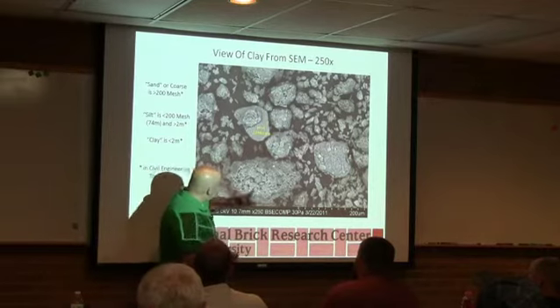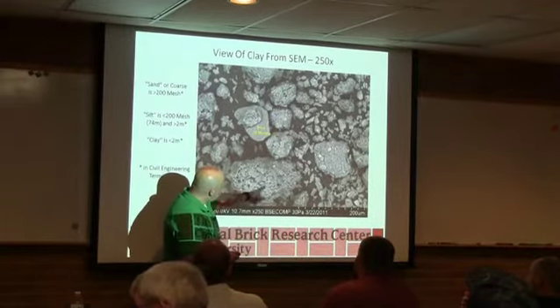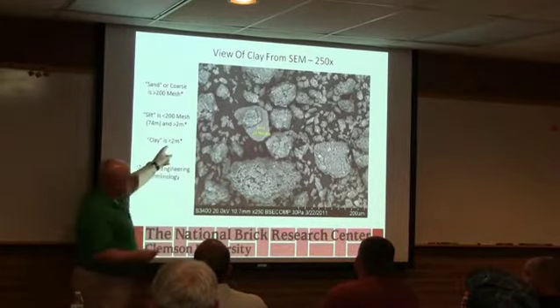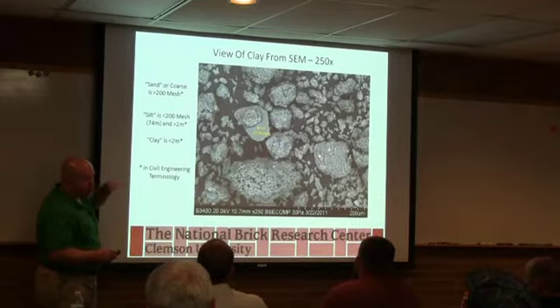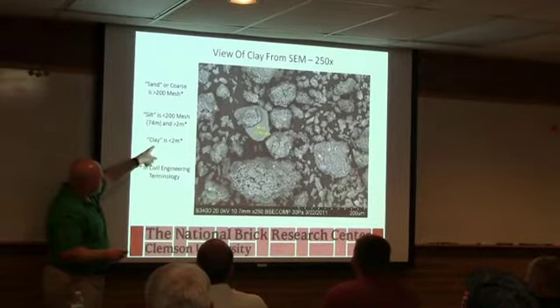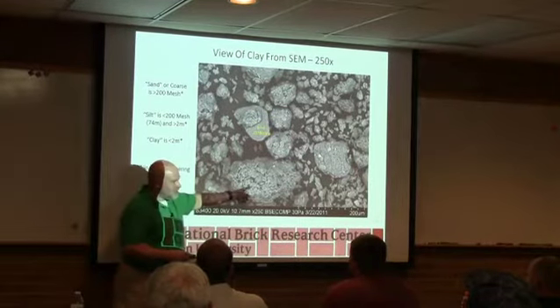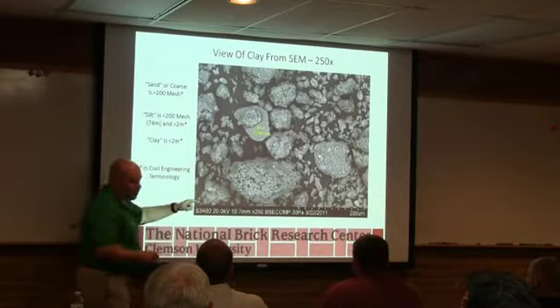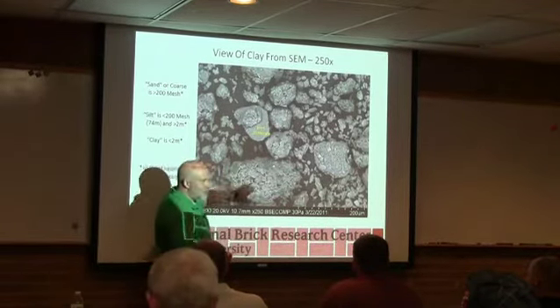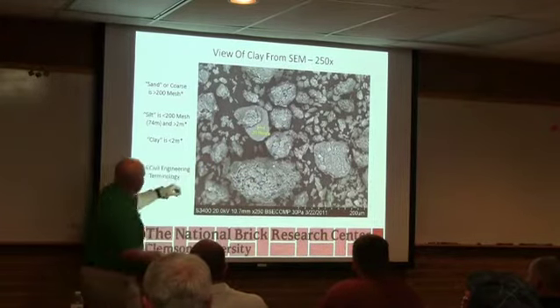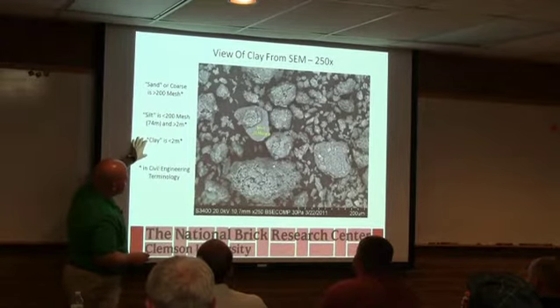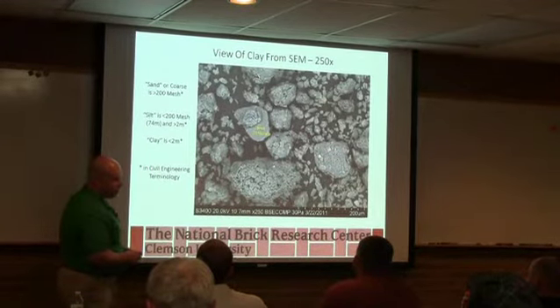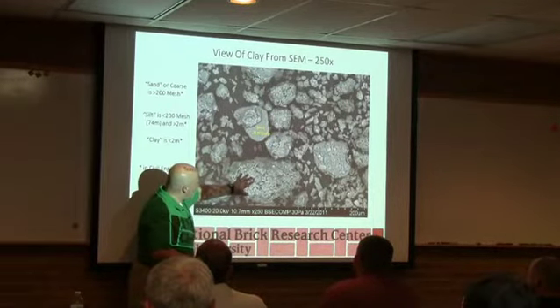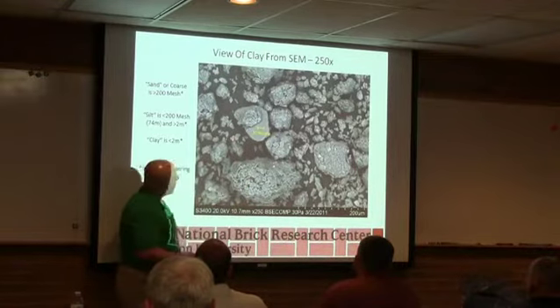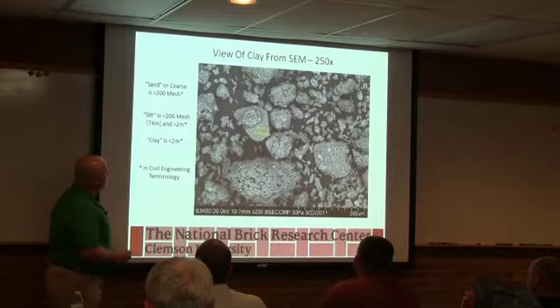Now, the other thing to think about is if you look at this, we would call this agglomeration. So these little clay particles, and this is important for a lot of things. That's part of where plasticity comes from in the material. The little particles have surface charge, and they like to stick to each other, and they like to stick to the bigger particles. Okay, so when they're doing that, they're not necessarily giving you all the benefit you would expect for each of the size. So the clay size fraction is primarily what's responsible for the green strength we're looking for. Okay, and there are things you can do through mixing, water addition, deflocculants to help break up those agglomerates. But that's something always to keep in mind when you look at the raw material. They do like to ball up on us.